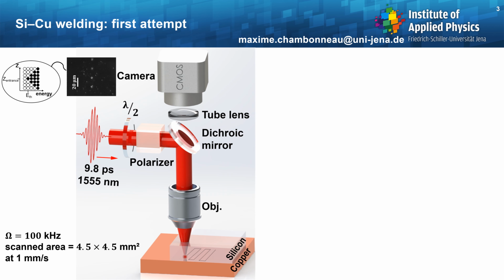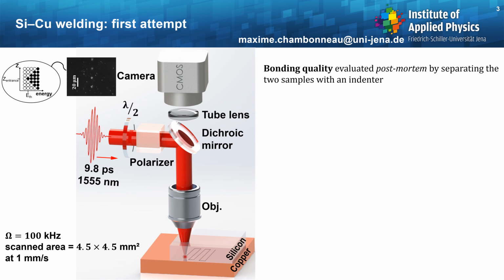To do so, we will illustrate semiconductor metal laser welding with silicon and copper, and we will employ the following arrangement, which relies on 9.8 picosecond laser pulses at 1.55 micron wavelength, for which silicon is totally transparent. Then we adjust the input pulse energy by means of a half-wave plate and a polarizer before the beam is focused at the interface between the two materials with an objective lens. This objective lens is also used in a customized microscope working in dark field and in reflection, which enables us to position the geometrical focus with respect to the entrance surface of silicon. And then the bonding quality is evaluated post-mortem by separating the two samples with an indenter.